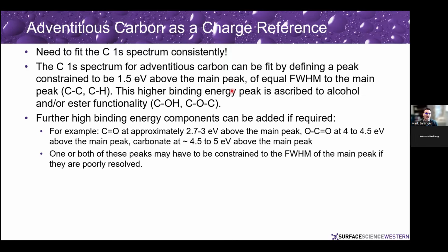And again, we'll have the main peak. We're going to have another peak constrained to be about 1.5 eV above the main peak, and that's our carbon singly bound to oxygen, with an equal full width half max to the main peak. We'll have further peaks that can be there, ketones or other functionality. We're going to have carbonates sometimes present, and we may have to put those peaks in, and they may or may not have their full width half maxes constrained if they're only poorly resolved.